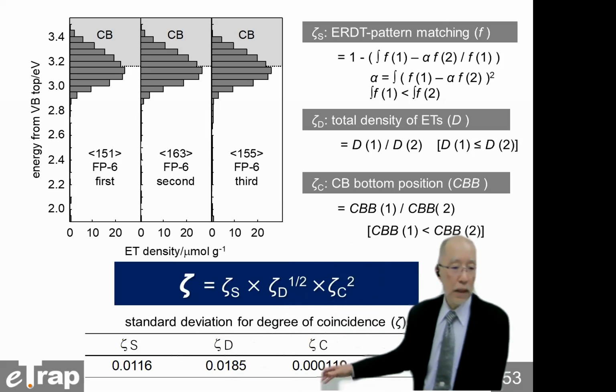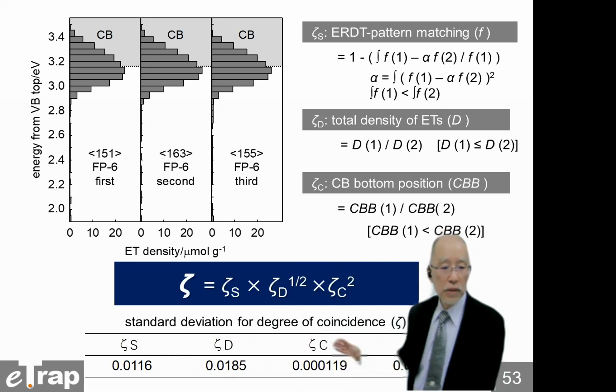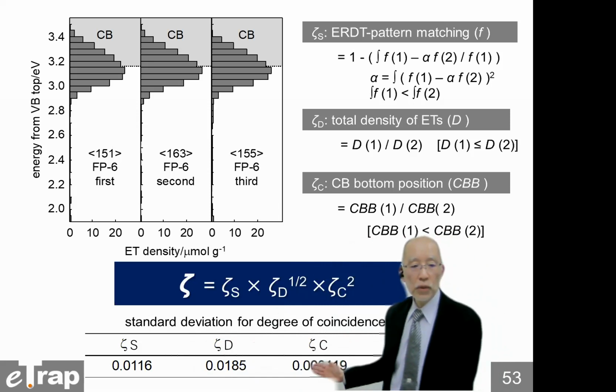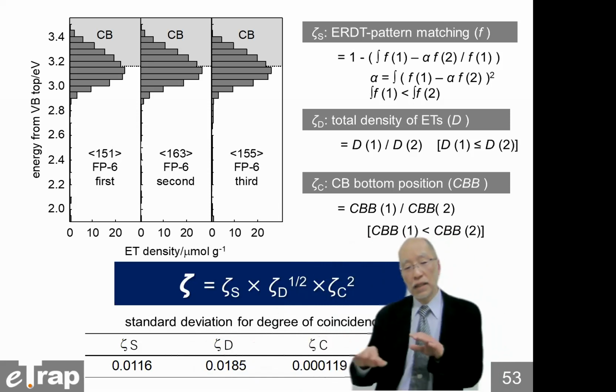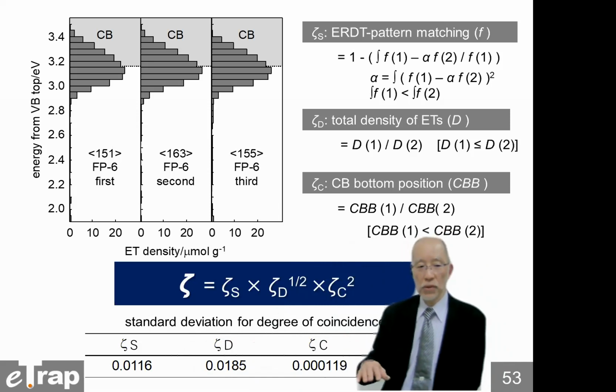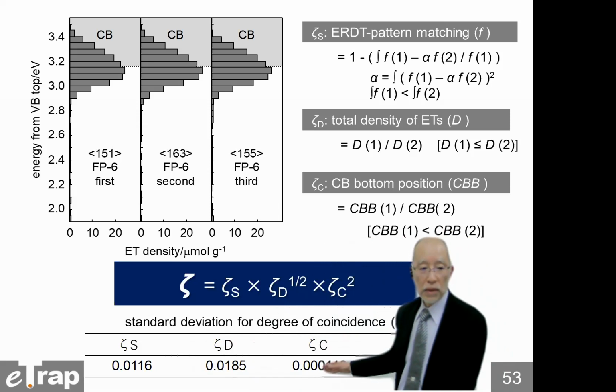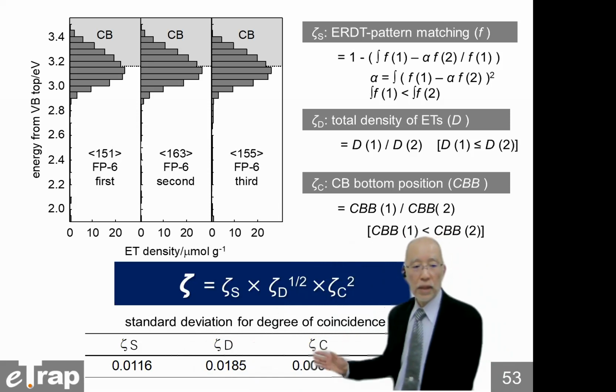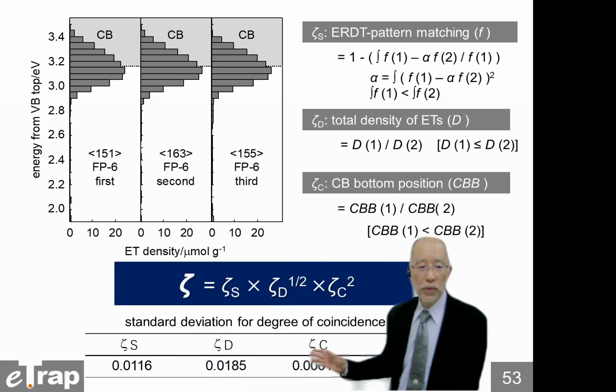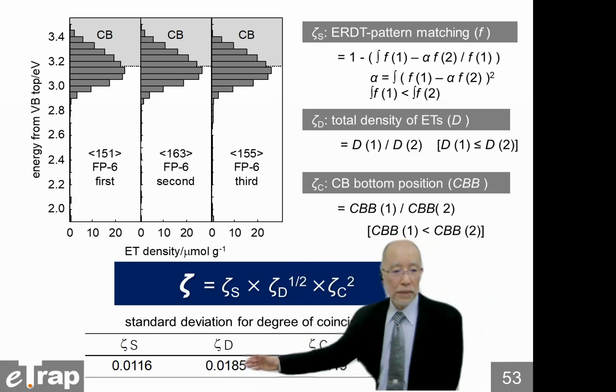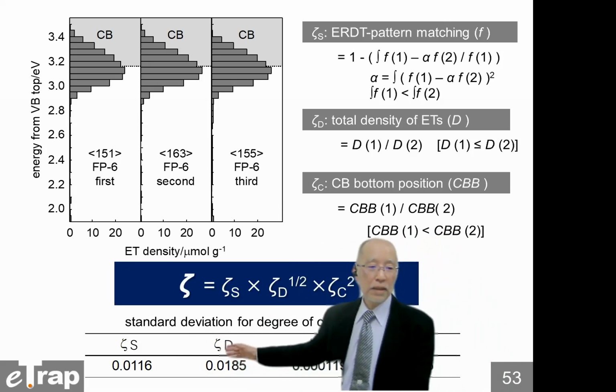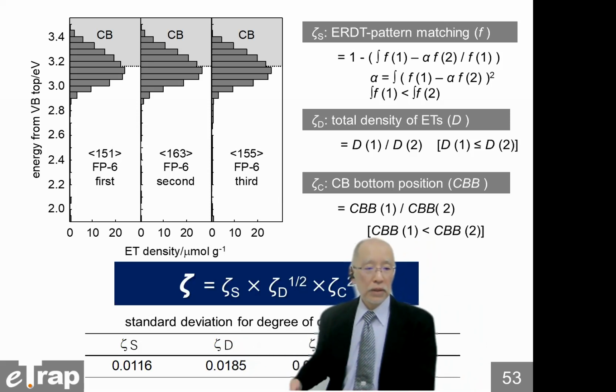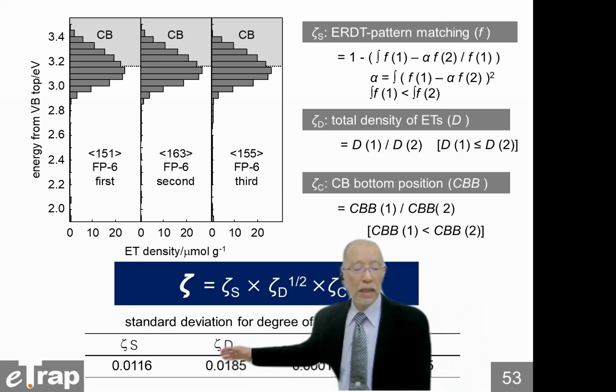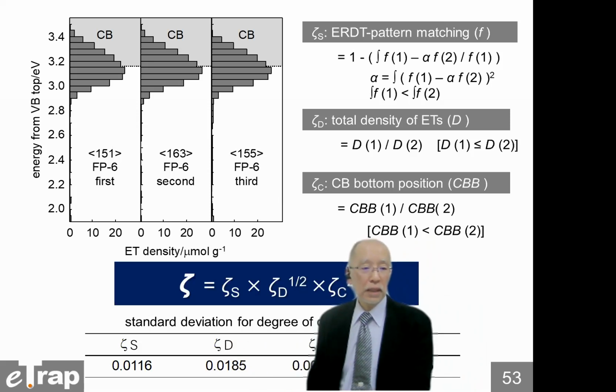the standard deviation is very, very small for CBB. If the bulk structure is the same, the CBB position is the same, so the position is almost the same for those materials. And there is almost no deviation. But the density is changing depending on the measurement time. So that has a bit higher standard deviation.